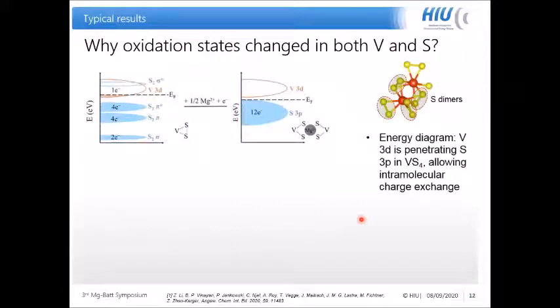This could be explained from the energy diagram of VS4. We see that the vanadium 3d orbitals are penetrating through the sulfur orbitals. With the overlap of these orbitals, we could have some intramolecular electron exchange, so that during magnesium insertion, the electrons from the outer circuit and also from the vanadium have moved, or jumped, to the sulfur 3p orbitals, because the newly formed sulfur orbitals lie below the vanadium one. That's why the vanadium has been oxidized during the process.